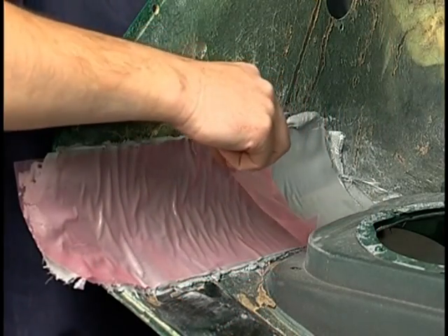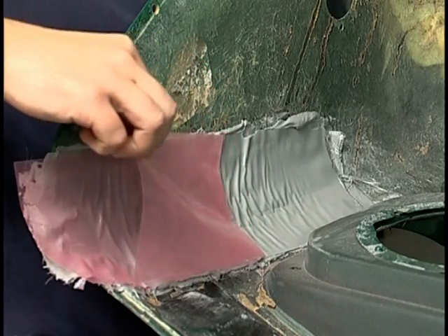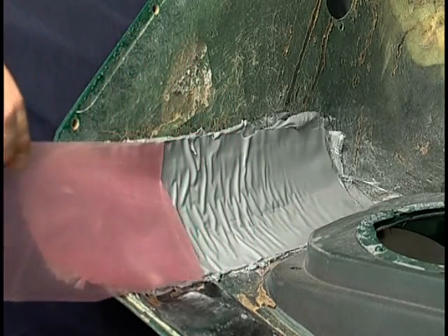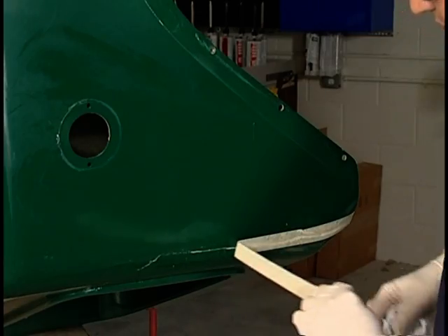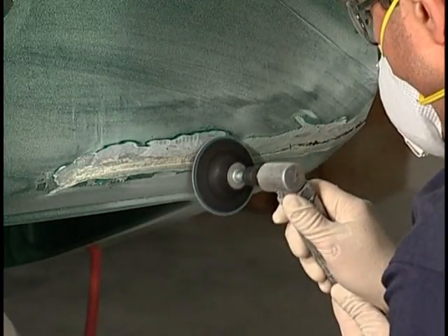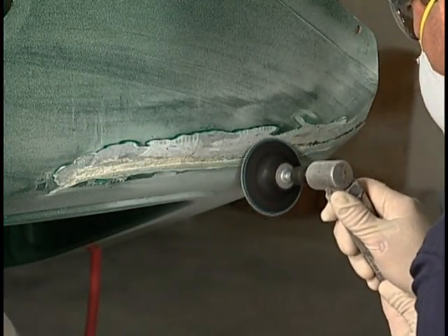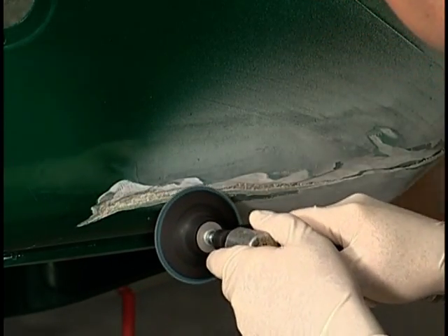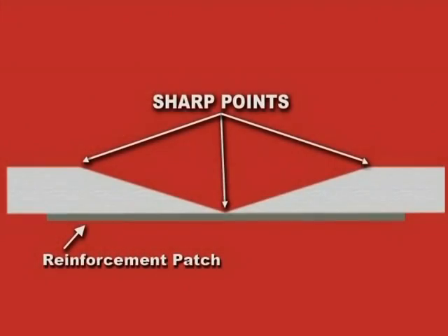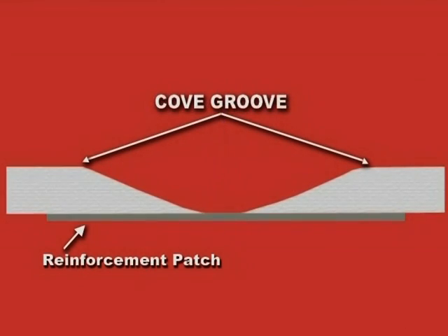Remove the plastic membrane and start repairing the front side of the damaged area. Remove the masking tape and grind the damaged area down to the backing patch, leaving no edges. Use an angle grinder with a 36 grit disc. Gradually taper the repair area rather than V-groove. V-grooving will leave sharp edges, causing an unacceptable repair. A gradual taper or cove eliminates the possibility of bullseyes or halos, usually caused by V-grooving.